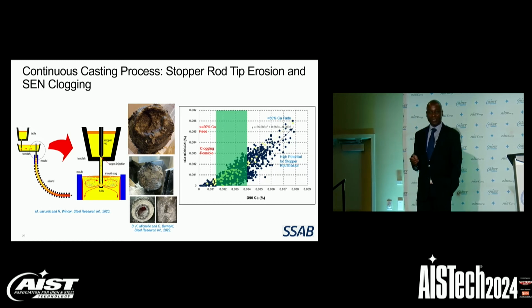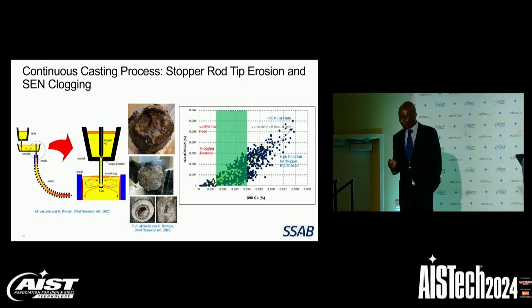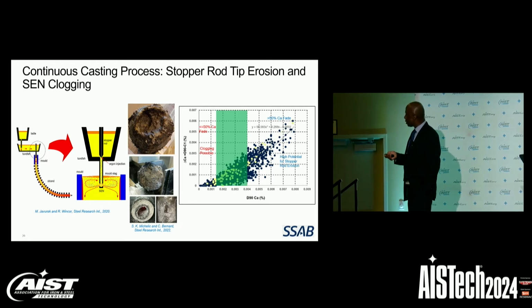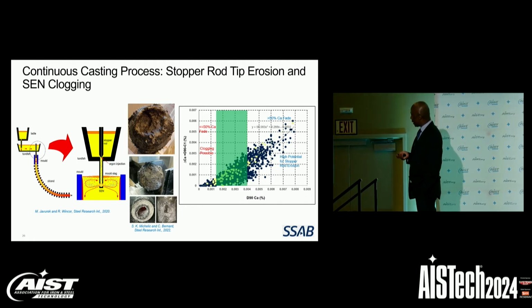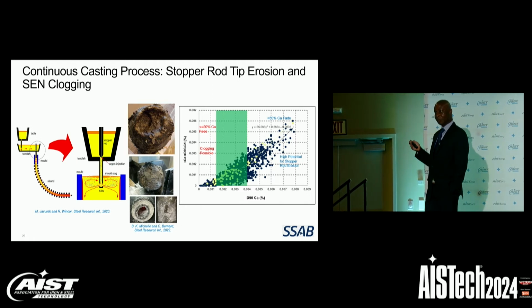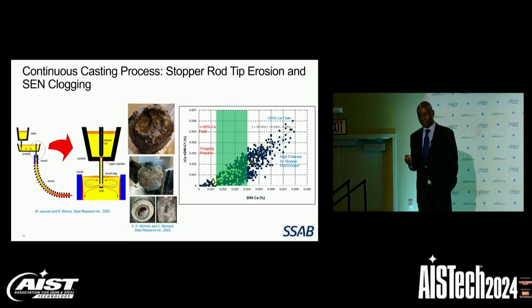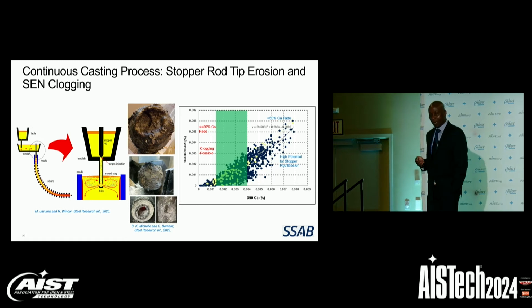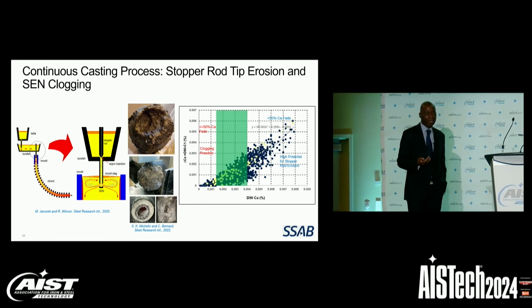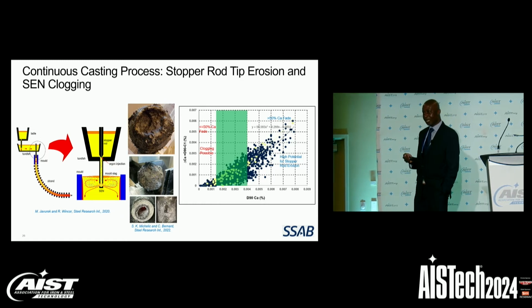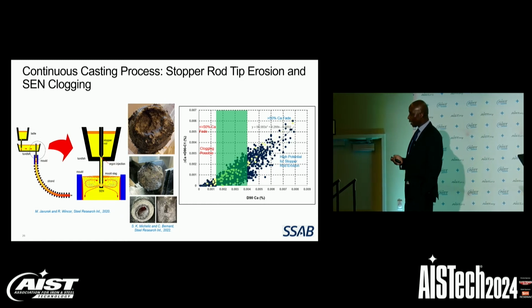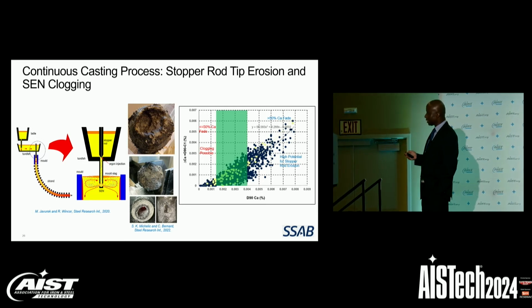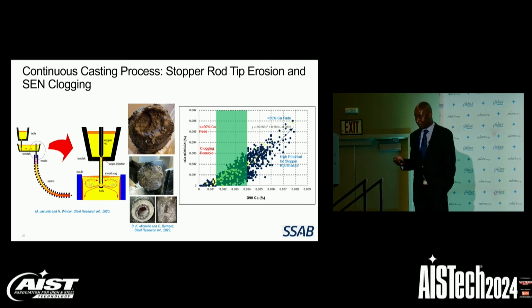But there are two incidents that can interfere with this flow dynamic. One is in the tundish: the stopper rod that is used to control the flow from the tundish into the mold can have severe erosion at the tip, leading to uncontrolled flow from the tundish into the mold. And the SEN that distributes the flow in a certain pattern in the mold can be clogged, choking off the flow from the tundish into the mold. By looking at the historical data, we found that these two events are related to the calcium content after calcium treatment in the ladle, and also to the amount of calcium fading that occurs during continuous casting.